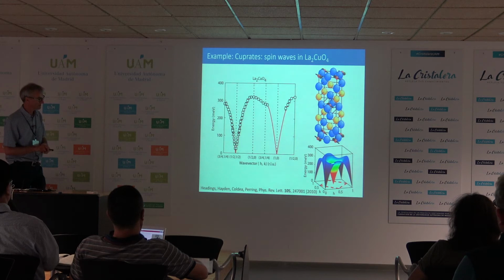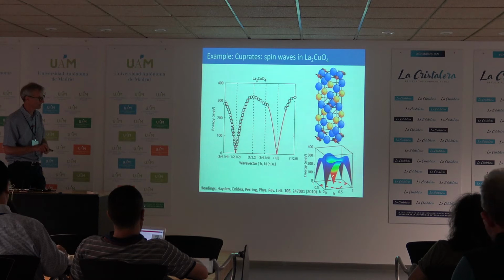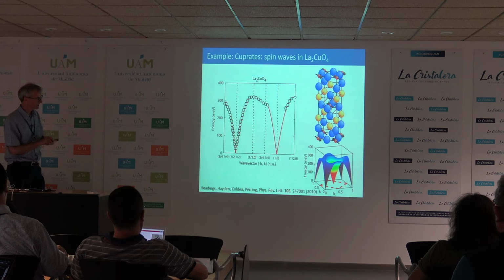So this is what you'd expect the spin wave excitations to look like, as I showed you before. This is now a two-dimensional diagram, obviously, and they're strong in the middle here. So this is the measured dispersion we have, and you can see the excitations are stronger at the half-zero position than the positions like quarter-quarter or three-quarters quarter. So this difference here indicates that there's some extra exchange. There isn't just a nearest neighbour exchange constant.